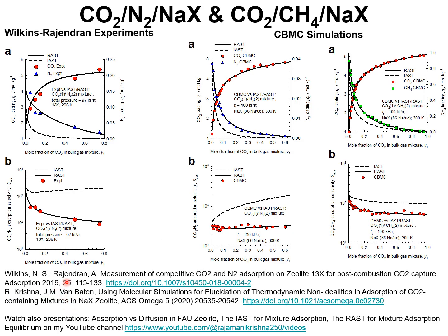Wilkins and Rajendran published experimental data for adsorption of mixtures of CO2 and nitrogen in 13X zeolite at a total pressure of 97 kilopascal and temperature of 296 Kelvin. The experimental data were obtained for varying amounts of CO2 in the bulk gas mixture. Here is a plot of the experimental data.